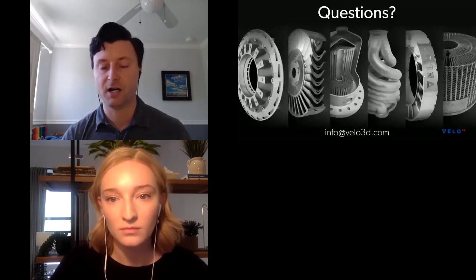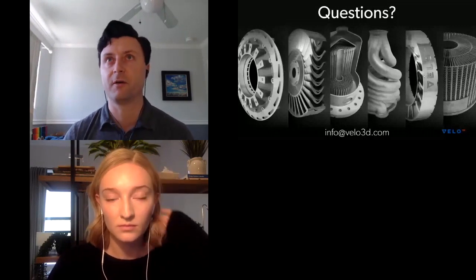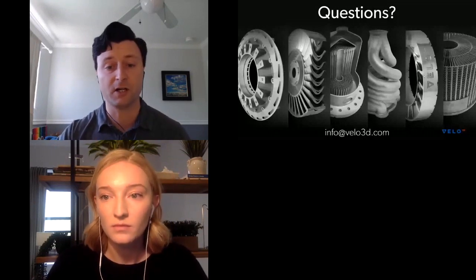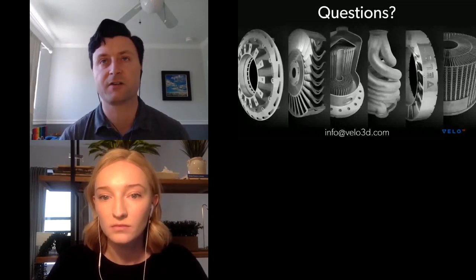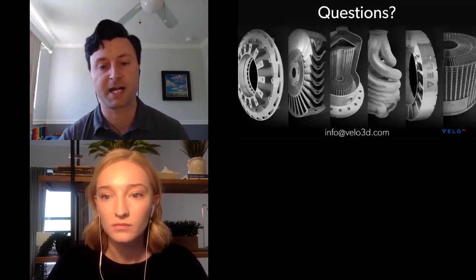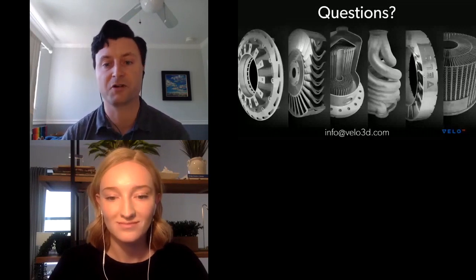And then on the second question, for a very low angle surface, if you're looking from like 10 degrees down to a 0 degree overhanging surface, our surface roughness there is probably between a 10 to 15 micron Ra in terms of the actual measurement.